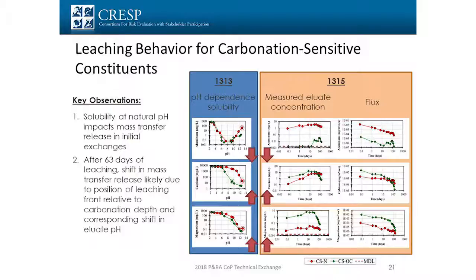And you'll see this shift at, say, 63 days over here. And we attribute that to the fact that the leaching front relative to the carbonation depth have kind of crossed. So you see that effect in these.